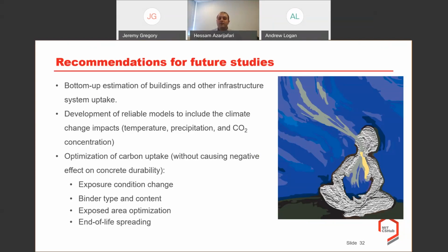And we don't see any negative effect on concrete durability because of the carbonation. We can consider and change the exposure conditions, the relative humidity, or the binder type and content, or the exposed area of the concrete structure. This is more flexible for architects, and for end-of-life spreading. So we can leave those demolished concrete for a longer period of time at the end of life to increase the carbon uptake of concrete without compromising the concrete durability.